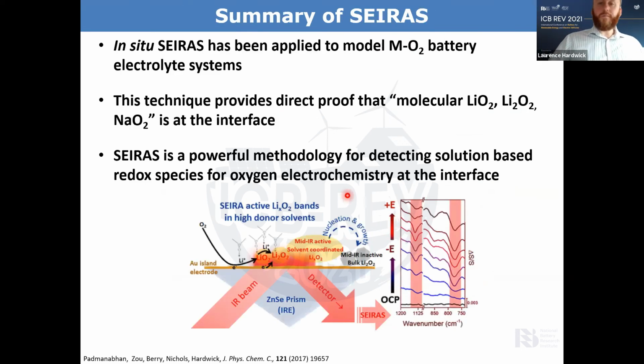So we've done a lot of work applying our surface enhanced infrared absorption spectroscopy technique to look at the speciation in metal oxygen battery electrolyte systems, and we've shown direct proof of the presence of molecular lithium superoxide, lithium peroxide, and sodium superoxide at the interface. We've seen that it's a very powerful methodology for detecting solution-based redox species for oxygen electrochemistry at the interface.